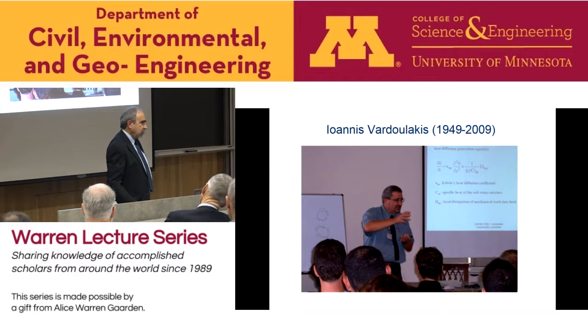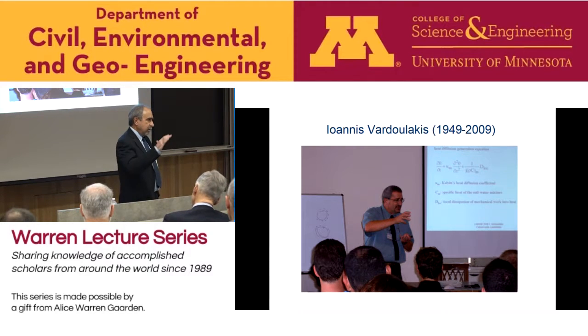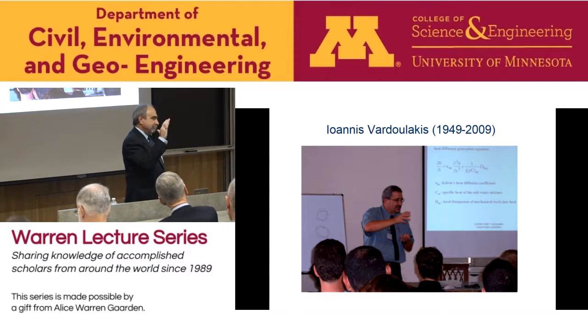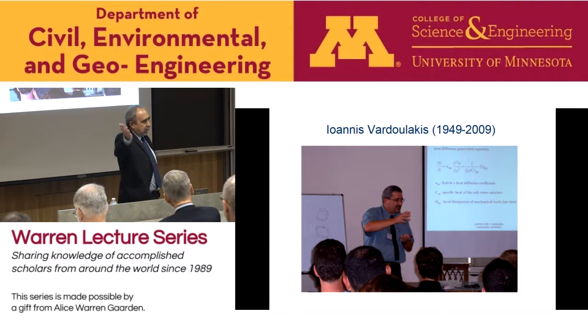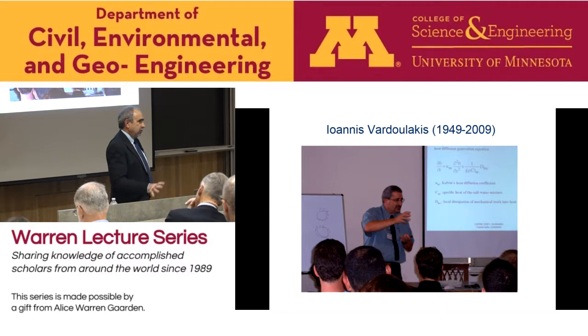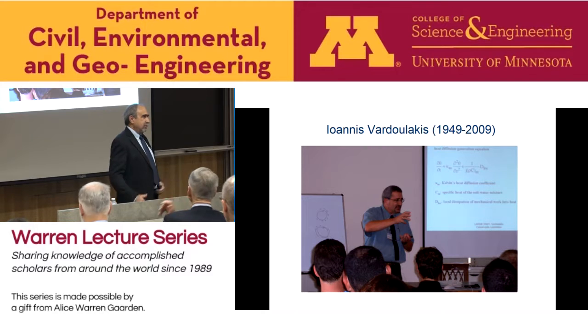Now, where that limit value will be, we did calculations for very weak rocks, and we showed that increasing the apparent toughness by 30 times, to 30 megapascal square root meters, we could still see the tendency to reach an asymptotic value, even for that high value. But of course, once it's fully developed, then as the fracture becomes longer, it will become less important, definitely. This is what I mentioned: we look at weak rocks, applications for short fractures, like for sand control, calibration tests, mini-frac, short fractures, and the confining pressure. The confining pressure at high stresses will push for more ductile material.